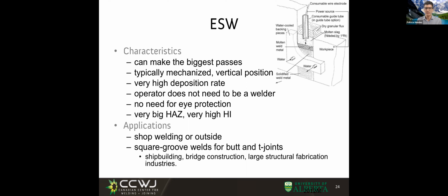Of course, this is mechanized. The way this swimming pool of molten metal moves up is through a mechanized system, with very high deposition rate. You don't need a welder to do this. It's just an operator. You don't need eye protection because everything is deep under the fluxes, and you don't even have an arc, right? This has, similar to electrogas welding, a very big heat affected zone.